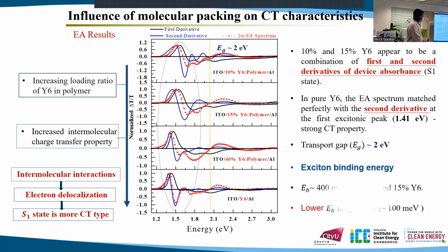And one more thing we can say about the exciton binding energy. Normally we define exciton binding energy as the energy difference between the optical band gap and the transport band gap. So this is the S1 state around 1.6, and this is the transport band gap. So we can expect around 400 milli-electron volt as the binding energy for the dispersed one. But when we increase the concentration, the S1 state itself becomes more CT. So we can say that it is around 100 to 200 milli-electron volt.